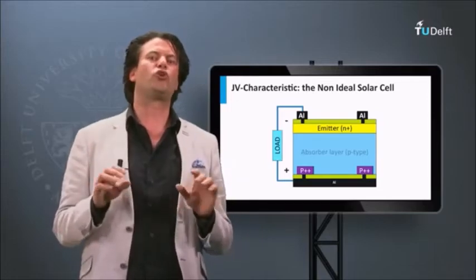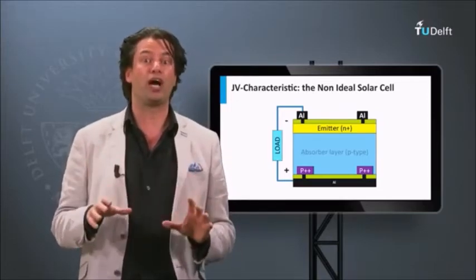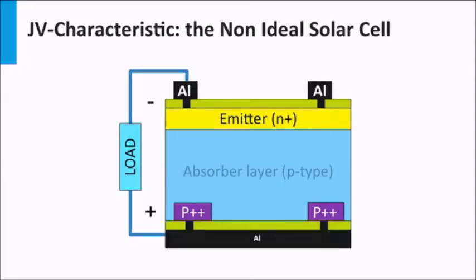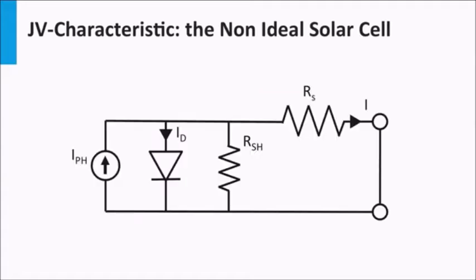The second resistance is the so-called parallel resistance, or also referred to as the shunt resistance. A shunt is a macroscopic defect in the solar cell which provides an alternative path for the generated photocurrent. Examples of a shunt are a crack through the semiconductor layers or a current path at the edge of the solar cell. In the electric circuit, the shunt resistance appears as a resistor connected in parallel with the current source and the diode. A low shunt resistance means that a large fraction of the photocurrent prefers to travel through the shunt, while a high shunt resistance means that less or no photocurrent is lost through the shunt.